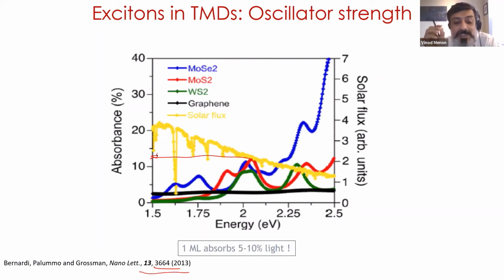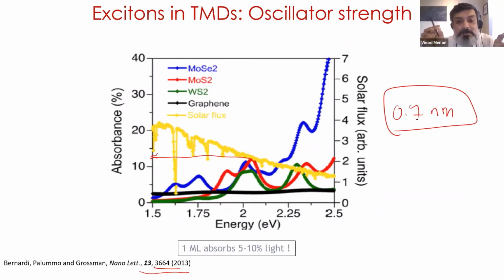So at these exciton peaks, this comes about because of the d orbitals that are involved in these transitions, which are highly localized, and hence you get these really large oscillator strengths. Just to put this in perspective, one monolayer absorbs about 10% light. One monolayer is less than a nanometer thick, about 0.7 nanometers to be precise. To get the same amount of absorption in silicon, you would need about 50 nanometers, or 50 times the thickness of this monolayer. So in the inorganic material world, this is, at least to my knowledge, one of the highest oscillator strength systems that is out there.